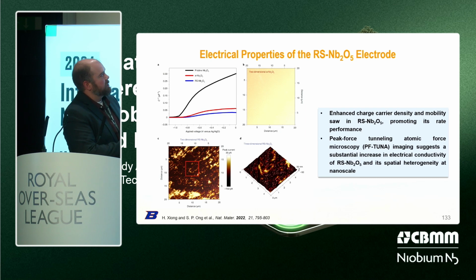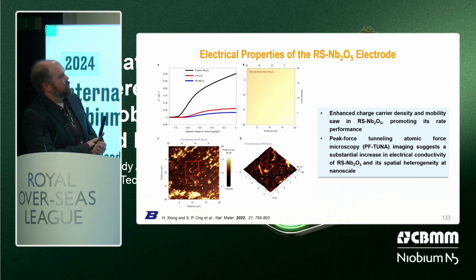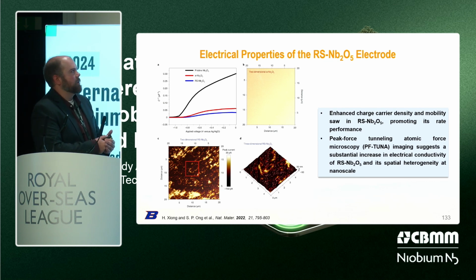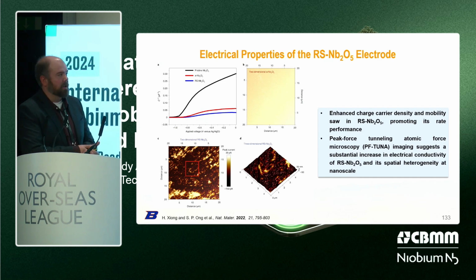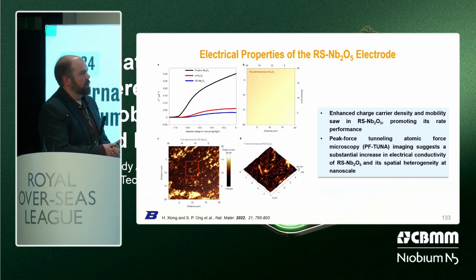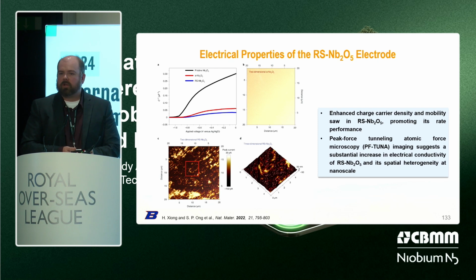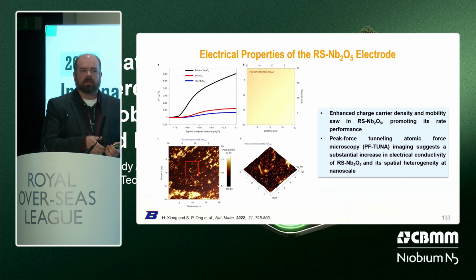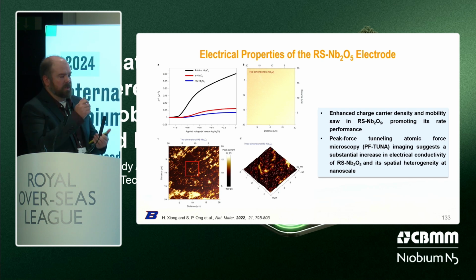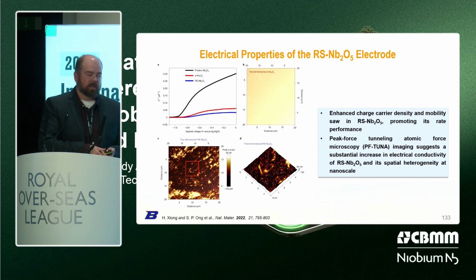So again, this is just a repeat of the last slide, but we wanted to see this visually, and so we used peak force TUNA. So what do we see on the amorphous structure? Well, at these same sensitivities, we pretty much have no signal associated with these amorphous niobium oxides that have been cycled the same amount of time as the rock salt ones. But when we put in the rock salt one, we see these pathways throughout the material where you have a greater transfer of electrons through the material at those sites. The peak force TUNA essentially is seeing how those electrons are going through that oxide material.